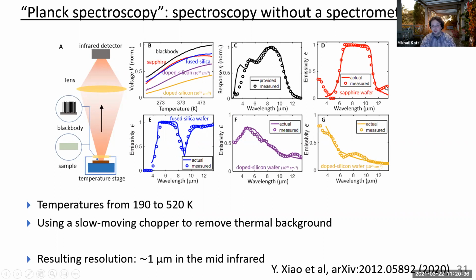And so, for example, here is our sapphire, and you can see in the symbols the spectrum that we recover. And here's this fused silica wafer. By the way, this feature over here in the fused silica wafer is a result of two vibrational resonances that are optically active. So it's kind of optical phonons, but this is an amorphous material, so it's maybe a little bit hard to call it phonons, but regardless, it's vibrational resonances. They're kind of the Reststrahlen band of the material over here. And so these fit very well.